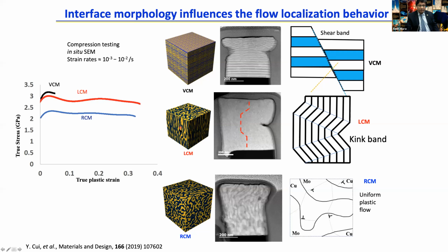In the lateral concentration modulation, we see a behavior that is characterized by these kink bands. You form these kind of nano kink bands. So you get plasticity, but not much strain hardening. Whereas in the random concentration modulation, which is like a bicontinuous intertwined morphology, two phases that are continuous all the way across, this is the case where we are able to spread plasticity all the way across the 3 dimensions. As a result, we are able to maintain plasticity across the material and not fail catastrophically. So there is promise in changing the shape and not just the size for a given material composition.